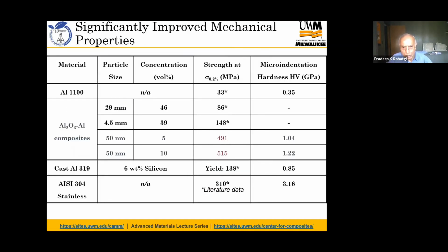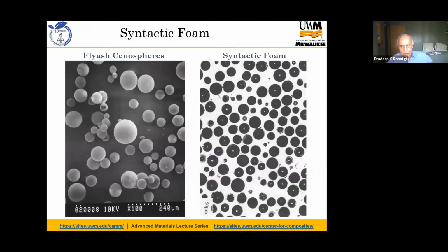I did talk about why in nanocomposites you get even better properties than micro. And this is a table that shows the properties you can get if you add alumina particles to aluminum. When the particles are micron size, the properties you can get are up to 148 megapascals. But if you reduce the size of alumina to nano size, you can get strengths as high as 500 megapascals, which is equal to steel. So you can get the same kind of strength as steel with much lower density, and that shows the power of metal matrix nanocomposites compared to monolithic materials.